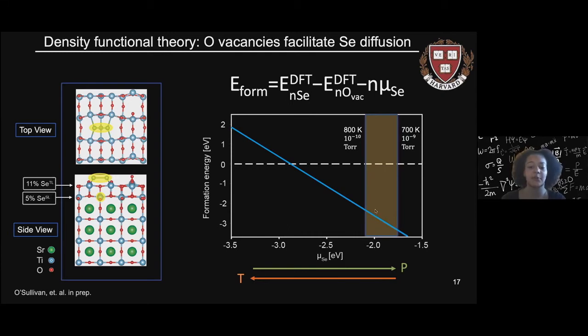And we note that our formation energy is negative under realistic conditions, which implies that the structure is indeed energetically favorable. So in summary, this supports our argument that selenium is replacing oxygen vacancies, and oxygen vacancies thus facilitate selenium diffusion, essentially supporting our measurements from STM and EELS alike.